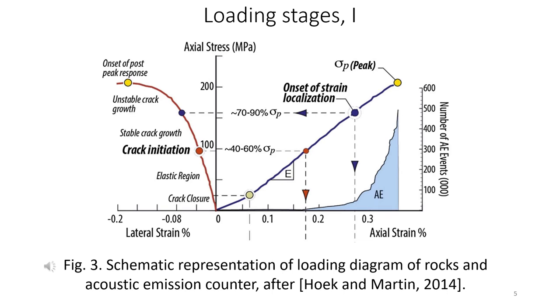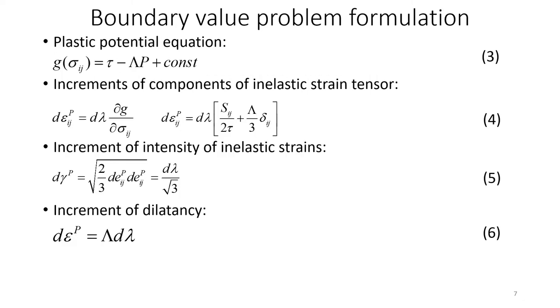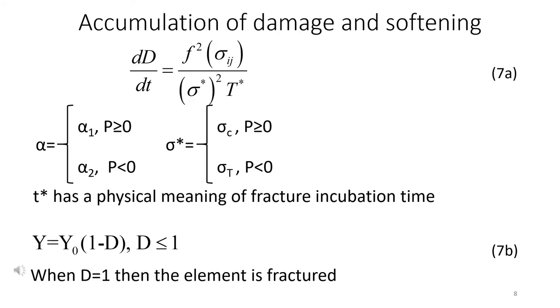Regarding the stages of uniaxial compression test, the complete stress-strain curve might be divided into several parts as illustrated in Figure 3. In this work, we apply a model based on the circumscribed Drucker-Prager criterion with a non-associated flow rule to describe the inelastic constitutive response of loaded samples. The model is coupled with a continuous damage mechanics approach to describe the softening of material.